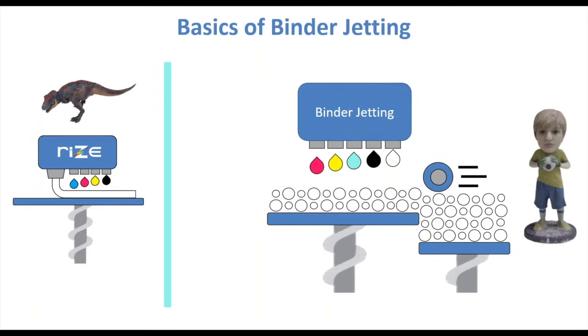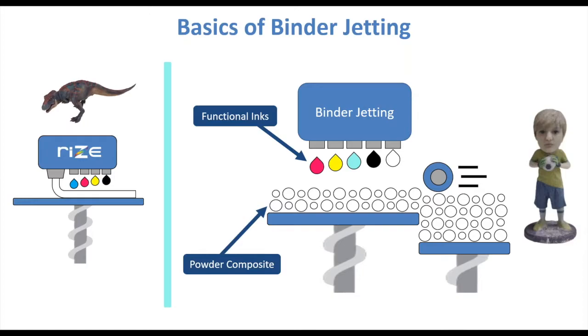So beginning with binder jetting, this process has been commercialized by the ProJet lines of 3D Systems machines. You may also know it as color jetting or CJP for color jet printing. This process also includes CMYK inks that are jetted through microscopic nozzles, the main difference here being the substrate. So instead of expelling the droplets onto melted plastic filament, you're dispensing them onto loose powder. So here the inks are actually serving two purposes. They're not only providing color, but they also have a binding agent that holds the particles of loose powder together so you can build up your part.